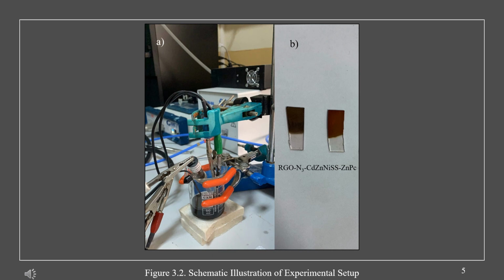After all electrodes were connected to the system with the help of crocodile clips, the cyclic voltammetry method was started at the scan rate of 100 millivolts per second for 10 cycles with voltage range from minus 1.6 volts to 0.7 volts. In the meantime, it's very important that the ends of the metal crocodile clips do not come into contact with each other. Otherwise, the system gives overload.